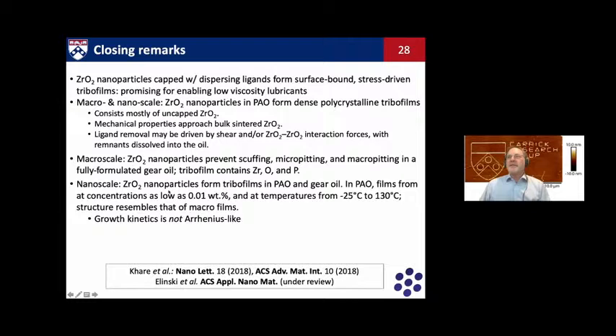At the nanoscale, we see that we can get films with concentrations as low as 0.01 weight % at low temperatures. And we even see growth of films in pure rolling contacts at the macro scale. So there are advantages compared to ZDDP. I didn't mention this, but the growth is also enhanced by surface roughness, which gives us more motivation to keep studying the mechanisms by which these films grow. So this work is published in these two papers, and there is a paper under review on the work on gear oil, which I hope will be coming to you soon.